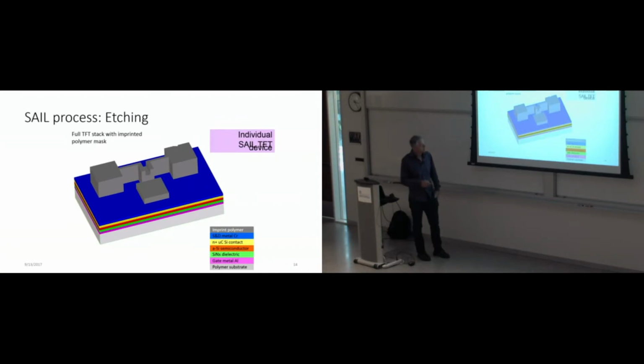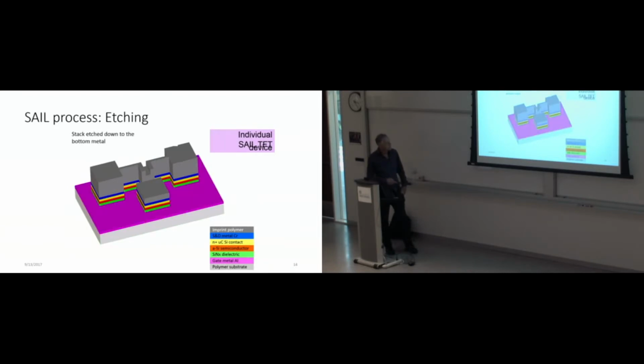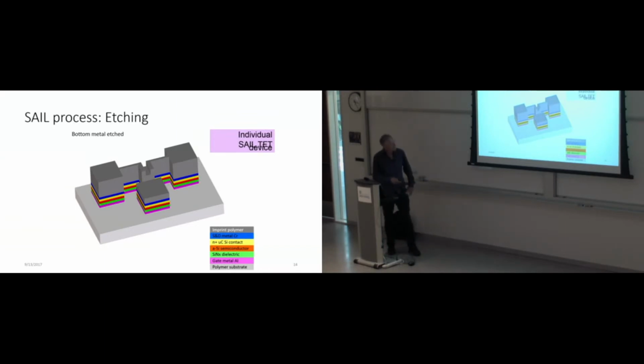You start with the stack of materials. This was done all in one go-round, wrapped up, sent through FedEx or whatever. Then we get the thing, we clean it off, and then do an imprint. You notice there's a bunch of different levels: 0, 1, 2, and 3. So what happens is we now etch down, and we etch away all but the lowest level, which in this case is the gate metal. We then etch away that metal and pattern it. Then we undercut, right through here. So now the gate pad, the source, and drain pads are isolated from each other.